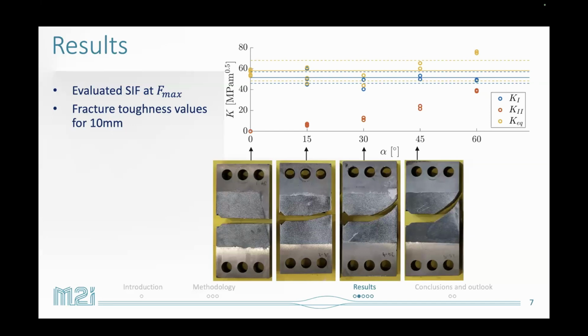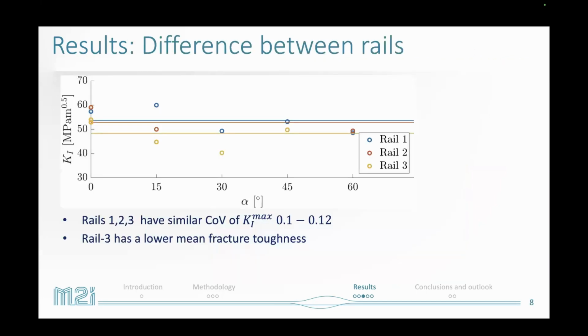So what you see in these 4 pictures are 4 tests corresponding to 0 up to 45 degrees. Obviously, when we have a pure mode 1 test, we will have a straight crack, which was also expected. And then with increasing crack or applied loading angle, we get a deviating crack path. It's also interesting to see that, especially at these higher angles, it's also not a straight line. So there's a slight curve in this crack path.